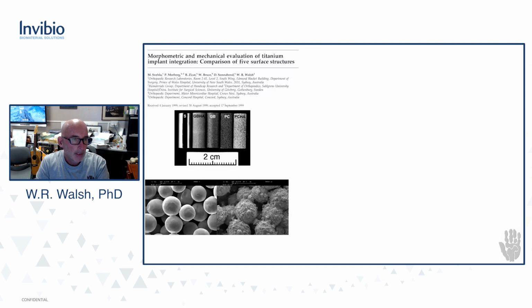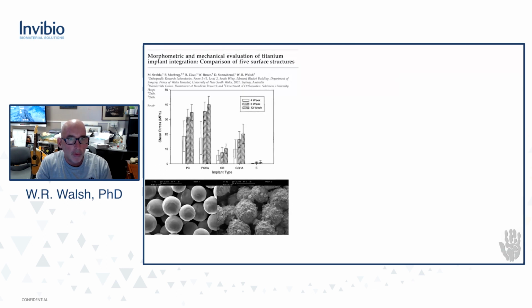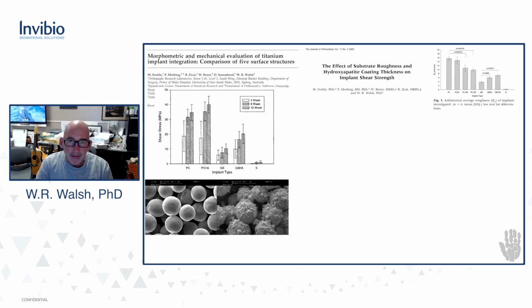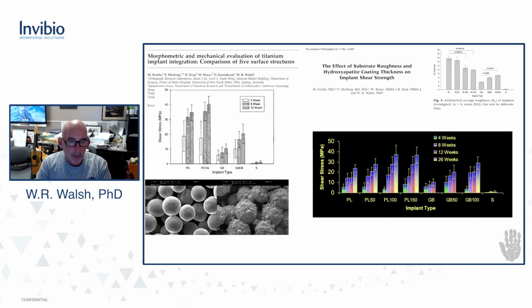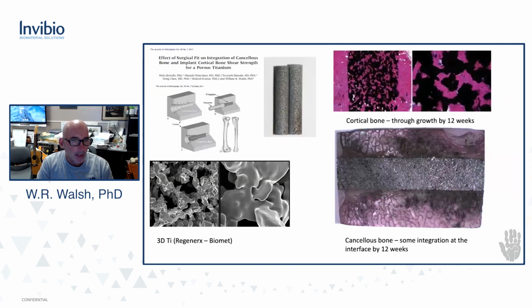We've been using this model for countless times, and this is 3D porous titanium beads with hydroxyapatite, the original DePuy Porocoat. And we looked at the mechanical properties and the benefit of adding hydroxyapatite, or the potential, no statistical difference, but a benefit on a grit blasted structure. This is a smooth structure. And we've looked at different coating thicknesses with the exact same model, changing the plasma sprayed coating of hydroxyapatite from 50 to 150. Again, classic hip replacement stuff that's all been out in the literature for years based on these types of tests. But we've also used additive manufacturing with this model.